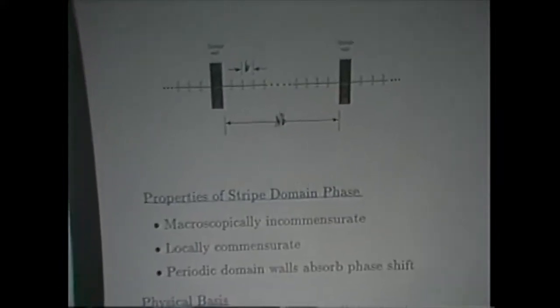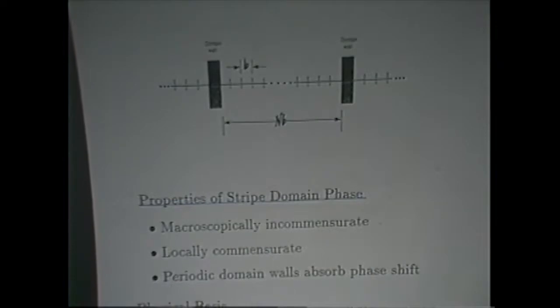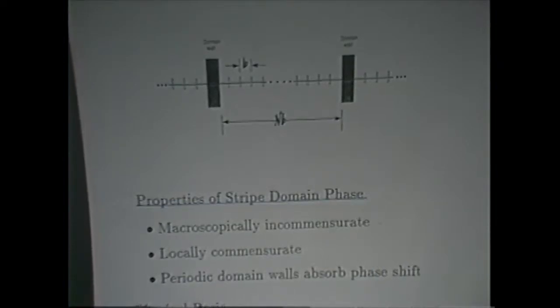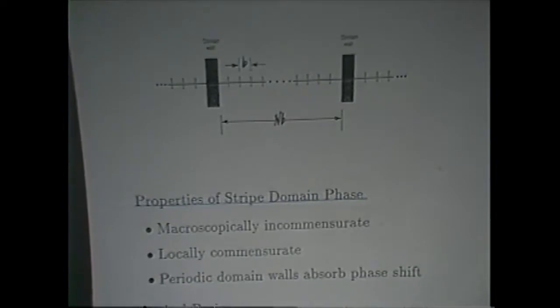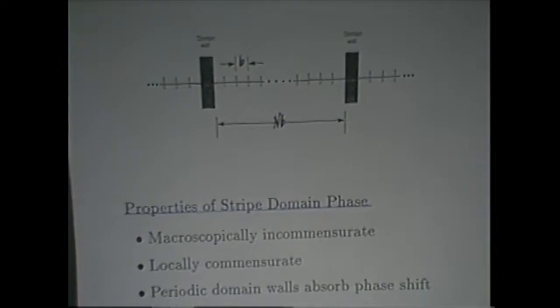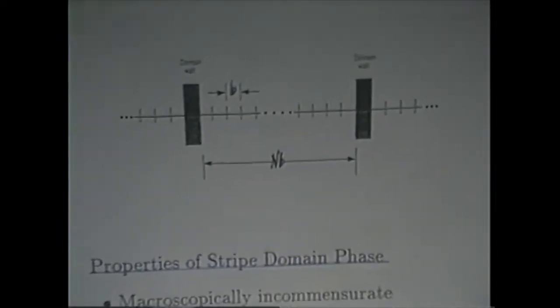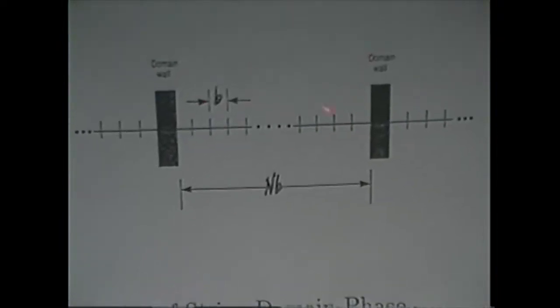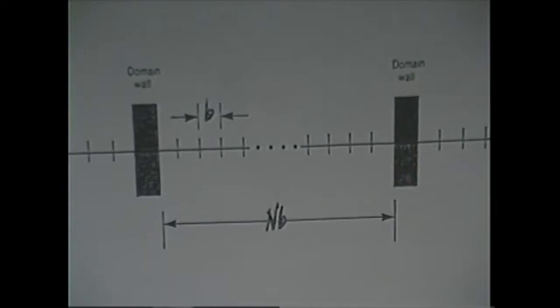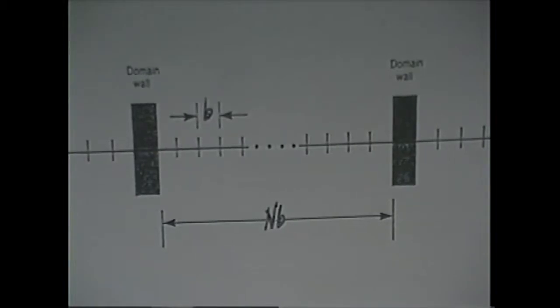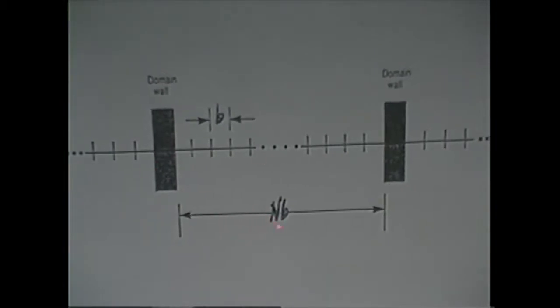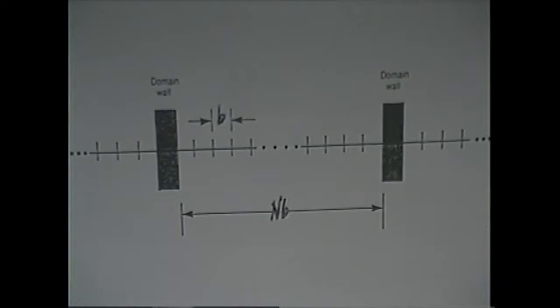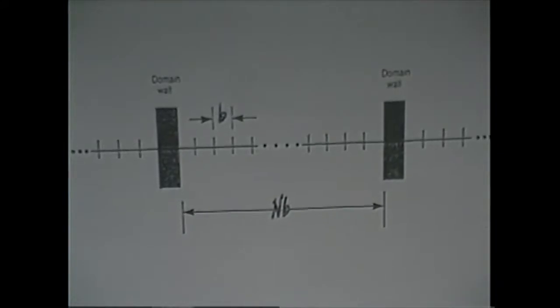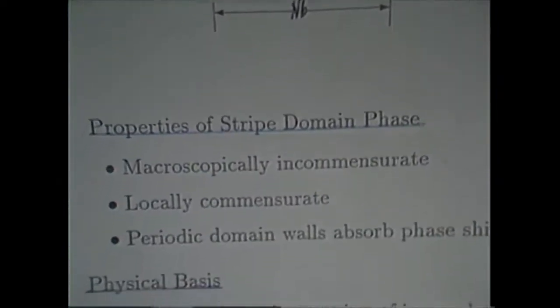What the stripe domain phase allows us to do is to take the bromine layer and allow its lattice constant to increase above that which it would have if it was commensurate with the graphite on a macroscopic scale. While at the same time, locally, there would be a commensurate registry between the bromine layers and the graphite. And now that's done by having a domain. Within this domain, we have a commensurate phase, and then there's a wall where the bromine is more dilute, less dense, so that the average lattice constant then will be larger. And by having the number of unit cells, capital N, decrease as the temperature is increased, then the average lattice constant of the bromine could grow. So that's the idea of the stripe domain phase.